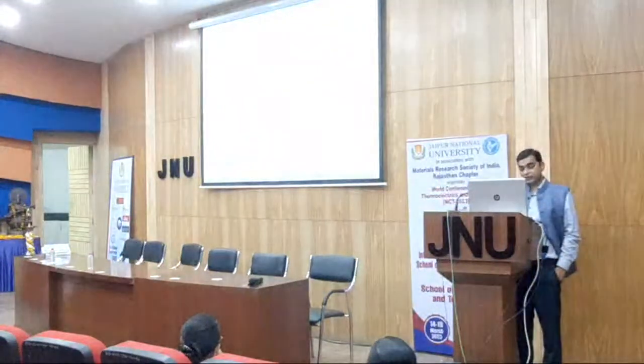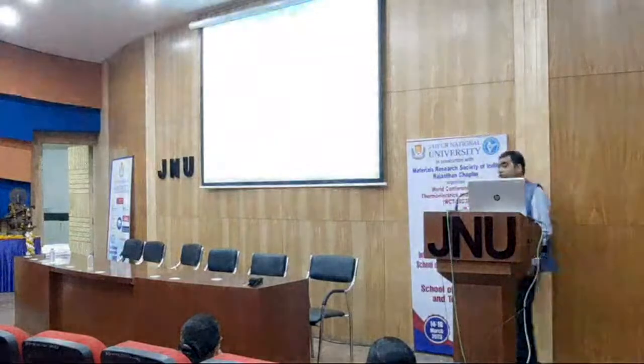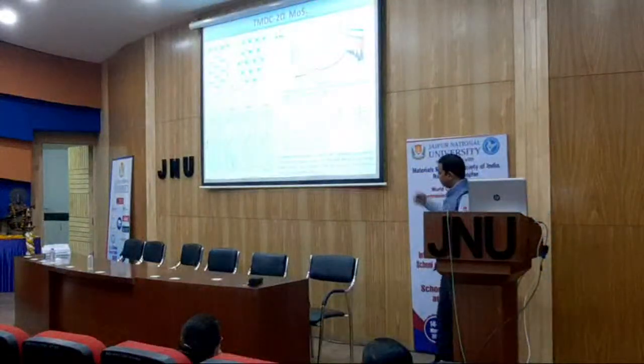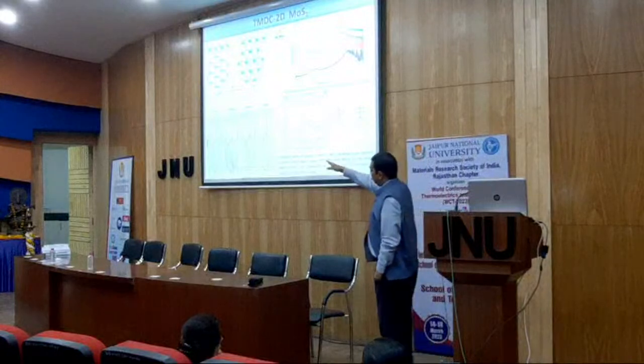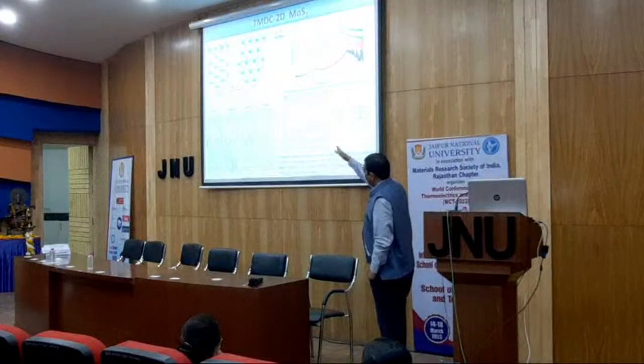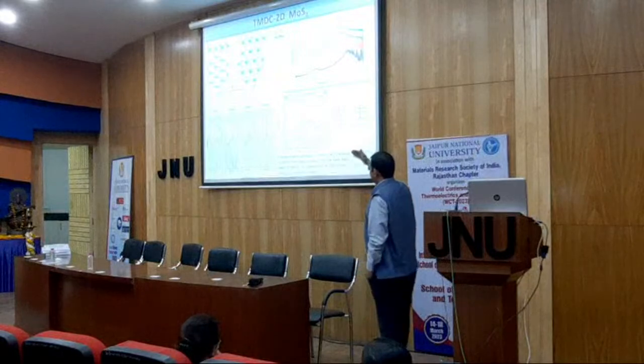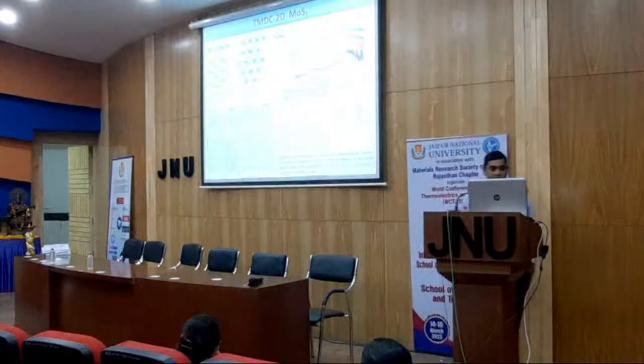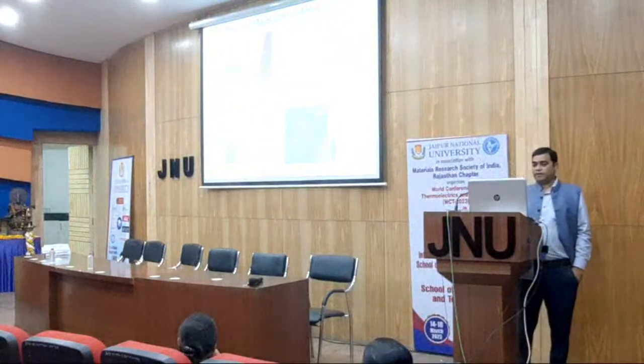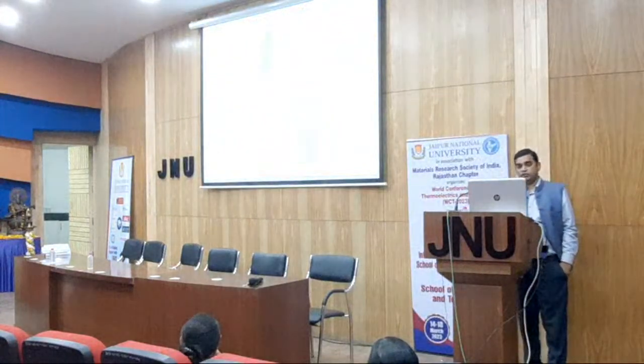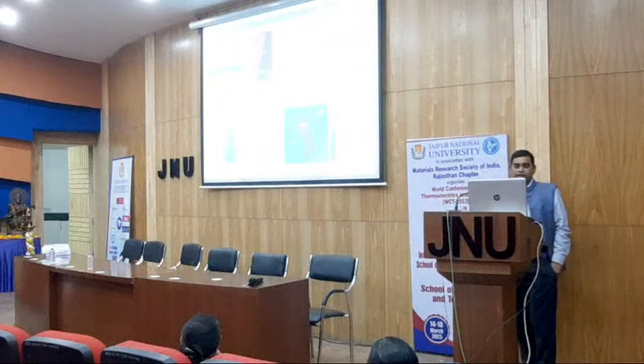So we have utilized this recipe to fabricate different structures. When we are talking about the 2D material, we have utilized MoS2, and bulk MoS2 band gap is 1.3 electron volt. As you keep on reducing the number of layers, you can see the band gap is slowly increasing and from indirect it became direct, and the band gap reached 1.8 electron volts. Absorbance is also increased. So we have fabricated this 2D MoS2, 3D gallium nitride broadband optical detector,